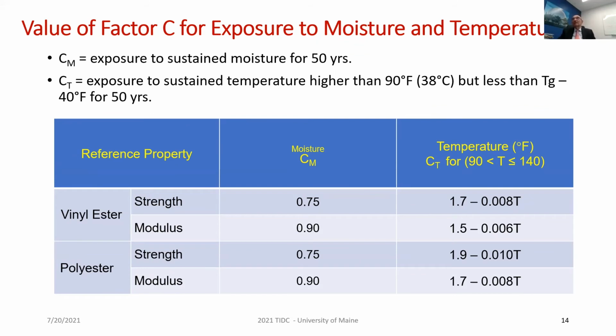The standard provides for two exposures, one being moisture and the other temperature, with values that, as you see, vary for strength and modulus, and also vary with the type of resin. And also in the case of temperature, it also varies with the level of temperature. And if you have both moisture and temperature, these values have to be multiplied together in order to establish the material adjustment factor for a product that is exposed to both moisture and temperature.